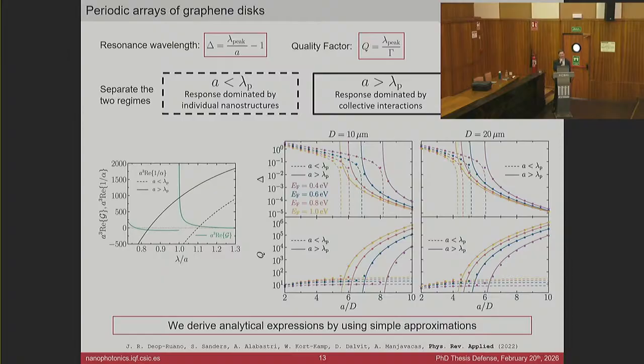Yeah, yes, that's another point. If you go to the limit where you mentioned where your resonance wavelength is super far away from the Rayleigh anomaly, you will have almost no nanostructure basically. But well, ideally you will still have a lattice resonance. In certain cases, we have seen for graphene that, for example, it has a steep dependence on the filling fraction, and if you choose a small filling fraction, your mode disappears from the spectrum basically.